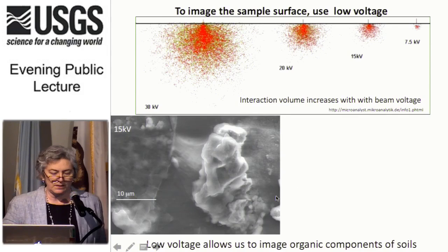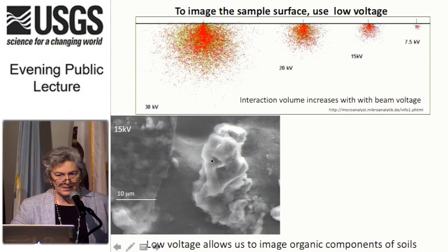But when you use the SEM to image carbon, you need to keep in mind that you want to look at something on the surface of things. And the normal voltage that the SEM is used at is about 15 kilovolts. And that's what this image was taken at. And you can see as you increase the voltage, the interaction, what they call the interaction volume, increases. And if you really want to look at something at the surface, you want a low voltage. And it's not until the last couple of decades that we've been able to use low voltage and image things.